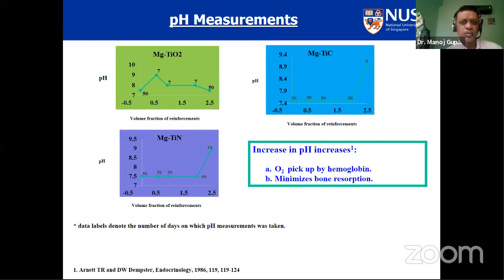So you choose the amount of reinforcement by looking at the mechanical properties and the corrosion properties. Don't add too much—if 0.5% of TiN can do the job, why go for 2%? Go for 0.5% only.